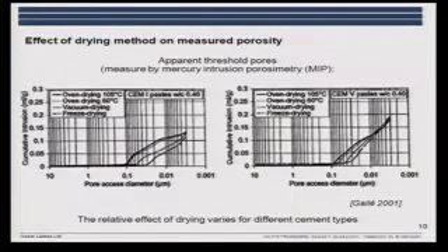Then, well, I know I'll show you these graphs before you've actually presented the methods, but let's just make a brief introduction. This is mercury intrusion porosimetry. You have a sample which you have dried in one way or the other. And then you press in mercury at increasing pressure. And assuming a given shape of the porosity, you can link a given pressure and the amount of intruded mercury to a relation between intruded volume and pore size.